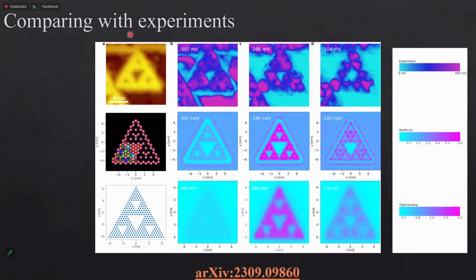Here I'm showing just a picture of the experiment. Here's one flake, and corresponding to this flake, we are showing the density of states. For both the experiments and the theory, pink is a very high density of states, and blue is low density of states. This is below the Fermi level, far below, so it's very low values of energy.